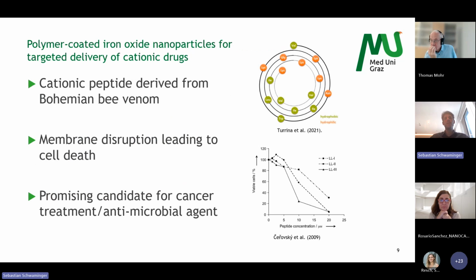Another system which we're using is a drug which was imprinted. In this case, it's the peptide lasioglossin. Lasioglossin is a cationic peptide which leads to the lysis of different cells. On the one hand, it's about tumor cells for drug delivery. On the other hand, it can also be used as an antibiotic for the lysis of different bacteria, mainly gram-negative bacteria. In this case, the membrane disruption distinctly leads to cell death with these kinds of peptides, which can be easily imprinted specifically with high affinity, then rebound to our molecularly imprinted polymer, and then used as an ideal candidate for cancer treatment.